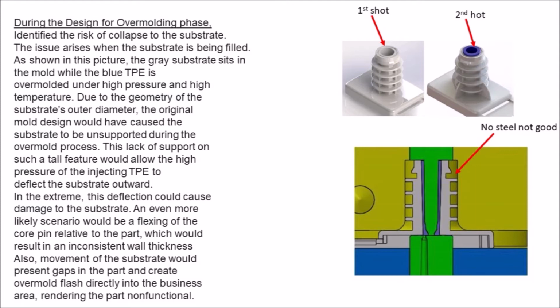During the design for overmolding phase, we identified the risk of collapse to the substrate. The issue arises when the substrate is being filled. As shown in this picture, the gray substrate sits in the mold while the blue TPE is overmolded under high pressure and high temperature. Due to the geometry of the substrate's outer diameter, the original mold design would have caused the substrate to be unsupported during the overmold process. This lack of support on such a tall feature would allow the high pressure of the injecting TPE to deflect the substrate outward. In the extreme, this deflection could cause damage to the substrate.